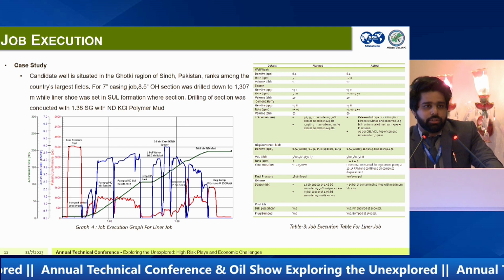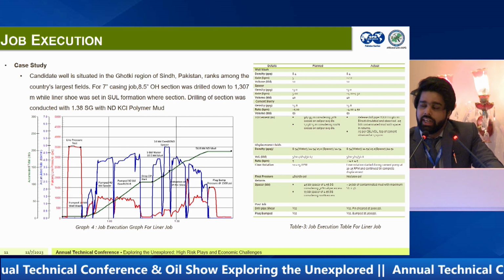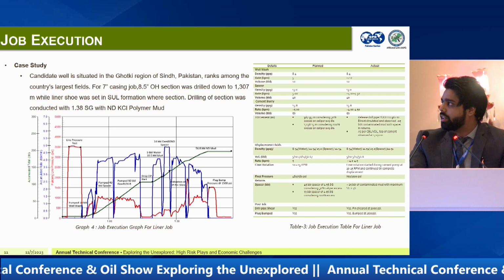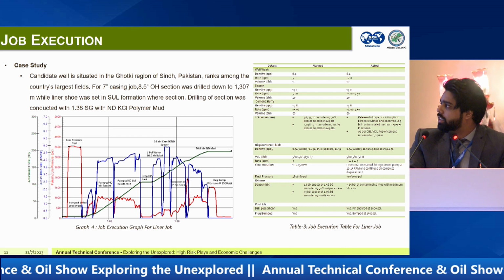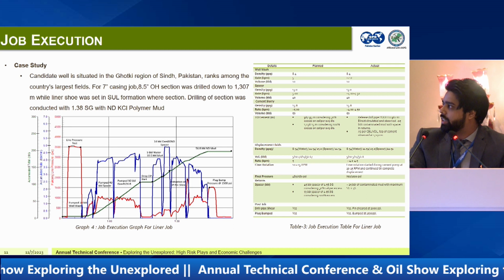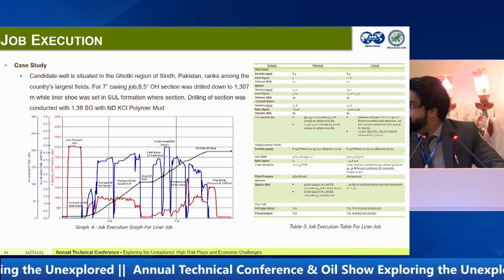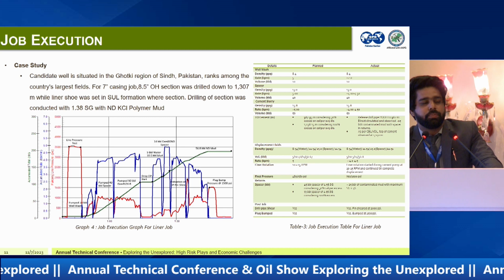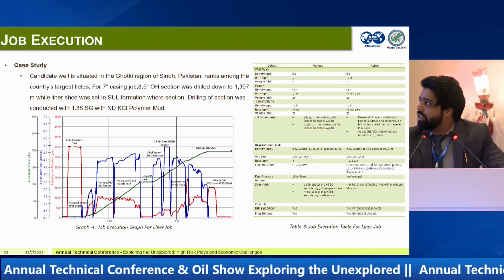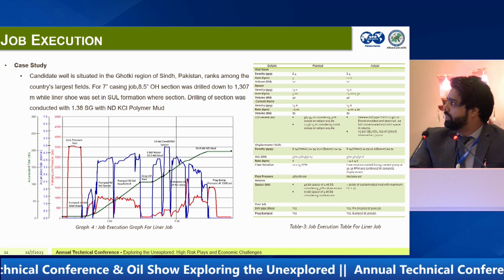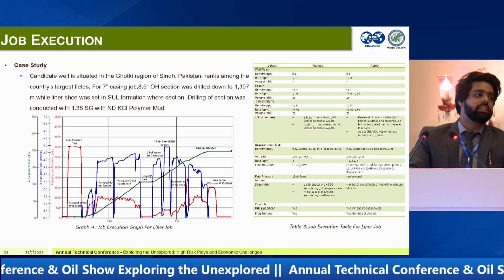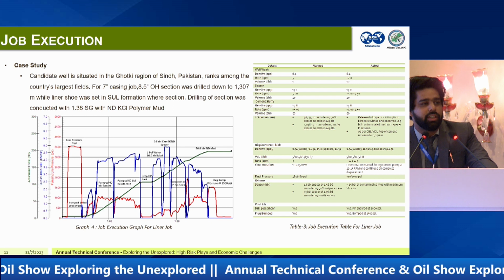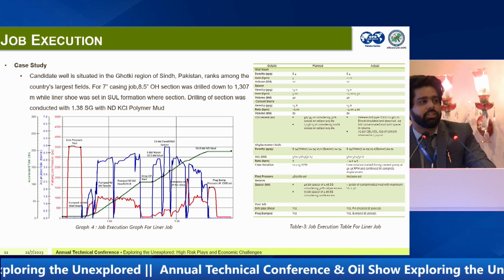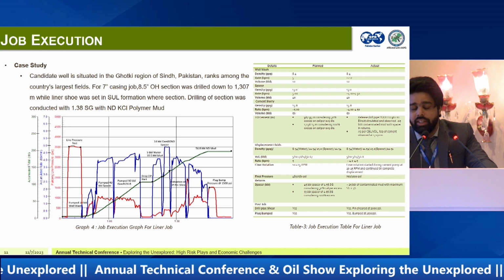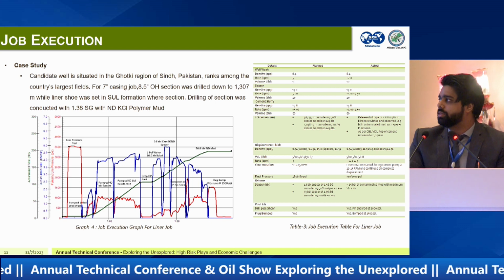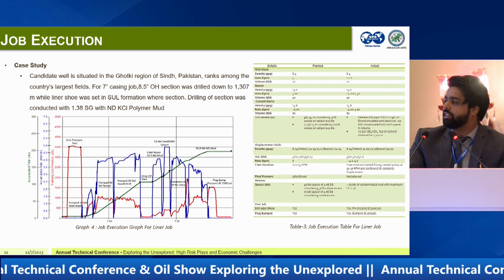Now, the job execution. We conducted a cement job in the Ghotki region of Sindh, in a 7-inch casing job and an 8.5-inch open hole drilled section. The job was conducted as per the planning, and you can see from the table that we achieved what we had planned. We successfully achieved the planning phase because the cement job depends upon the construction phase, and similarly, it is important to have good planning before proceeding towards the job.